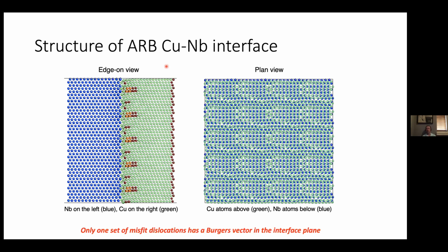So for this kind of binary system made out of two elements that we think we can model well, and having very little chemical complexity in and of itself, we think that these models are pretty good. Correlating the predictions from simulations to things that have been done experimentally, we can make direct comparisons. Now, if you were to go to something more complex, like replacing niobium with zirconium, things get much more difficult, because zirconium has, I don't know, a dozen intermetallic phases with complex crystal structures, and it's really difficult to come up with a potential that's going to represent that well. Our solution has basically been not to study copper zirconium and to focus on things that we can actually model, to make that correlation between the experiments and the simulations.